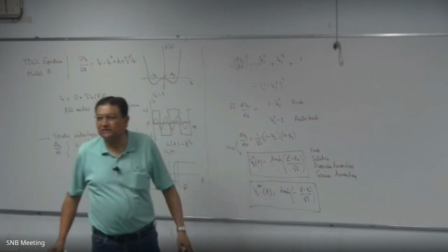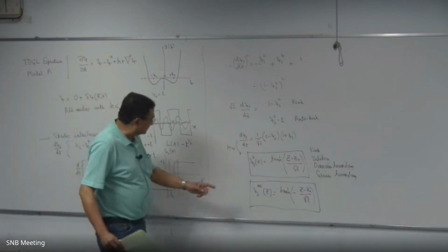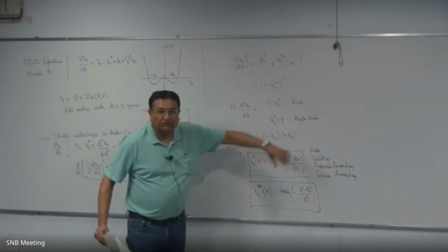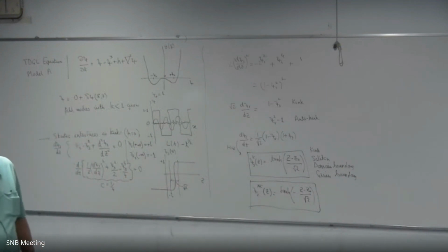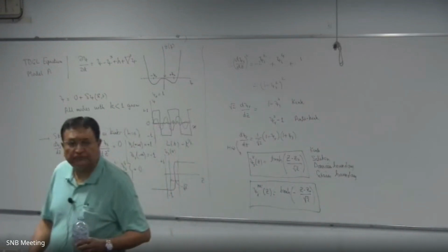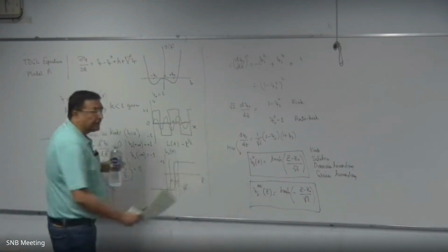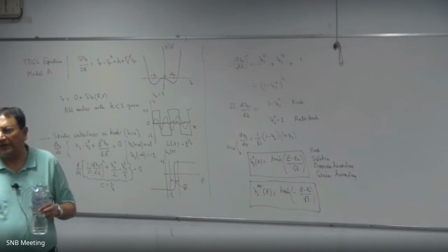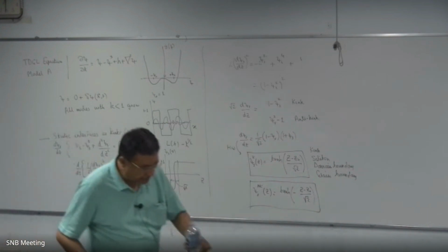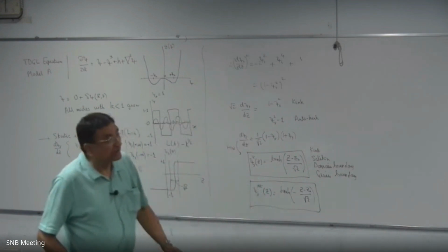And this answers, I think, Jaidev and Punyabhata's question yesterday. The logarithmic growth in one dimension comes from the fact that a kink and an anti-kink are only overlapping by the tails of this, and this tail differs from one by an exponential bit. And then you can write down the evolution equation for the distance between the kink and an anti-kink. This plus an anti-kink is only the solution when they are infinite distance apart. All finite distances will have a small correction. So that's why two kinks are actually not stable. I mean, in the sense, they will merge as a matter of fact.